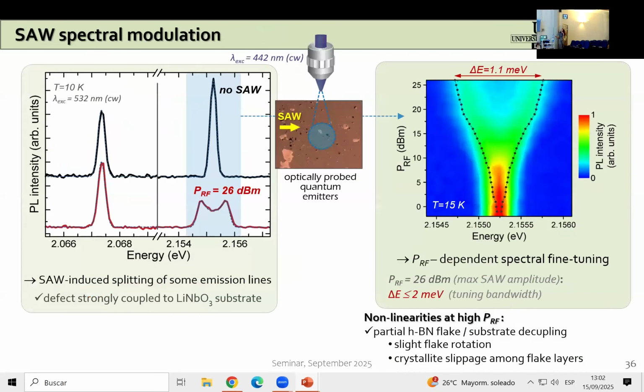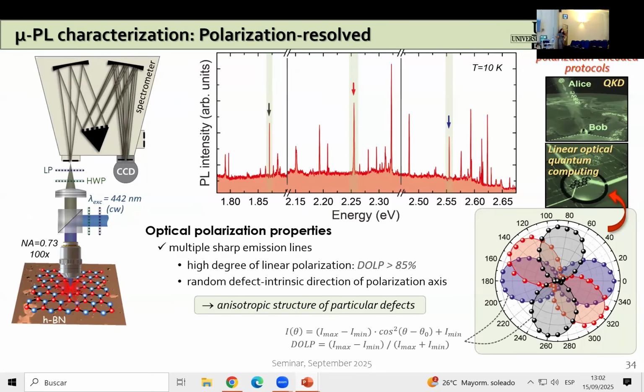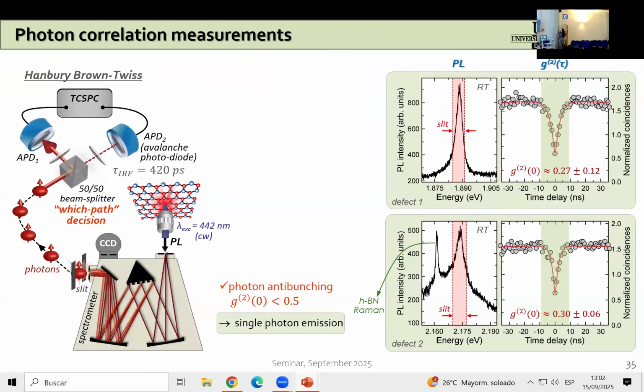Also, if we go back here, knowing that this strain tuning coefficient in the case of HBN material is quite large, this can also explain this large spread of the emitting peaks. Only a small amount of strain is already sufficient to shift these PL lines energetically by quite a large amount. So it really is feasible that the optical emission resulting in single photons comes from a particular defect species, as was shown by the DFT calculation, namely the nitrogen anti-site vacancy.